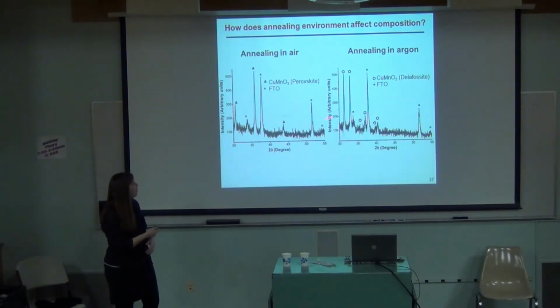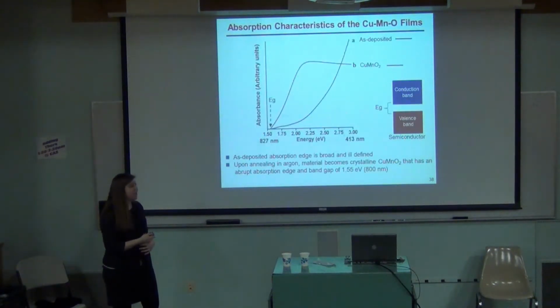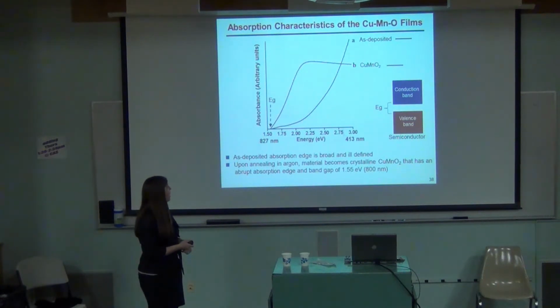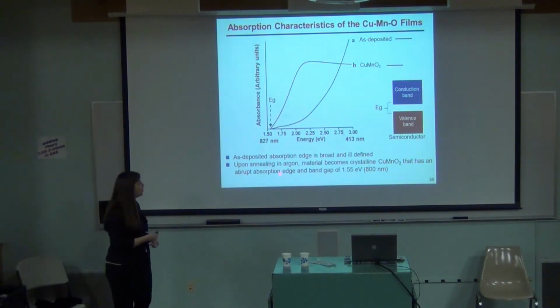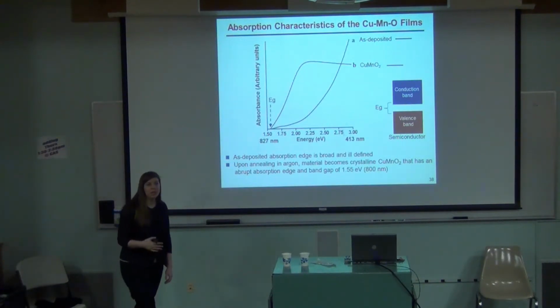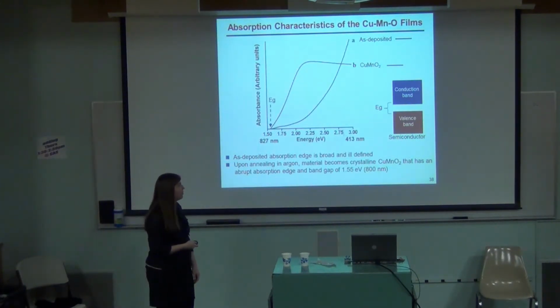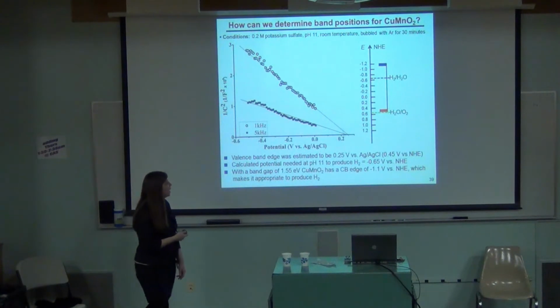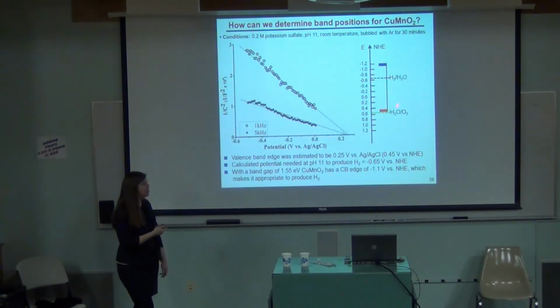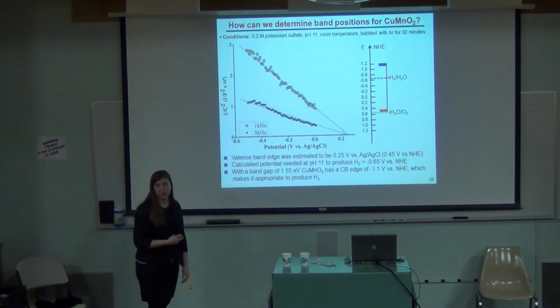XRD, again, I got perovskite and Delafossite, so it was pretty encouraging. And then I did some band gap measurements, and that was also encouraging because I was getting a band gap near where it should have been, about 1.55. So that was nice, and it had band positions that could do the hydrogen, not necessarily the oxygen, but that's okay because we just wanted a p-type material anyway.